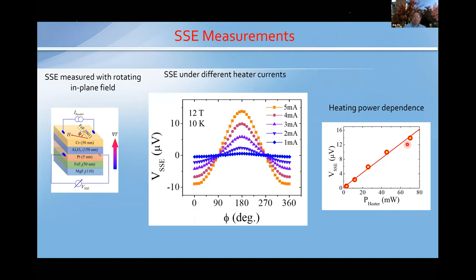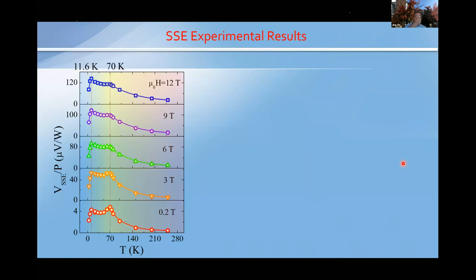Now let me present the data. I chose different applied magnetic fields along the easy axis, from 0.2 Tesla to 12 Tesla, which for iron fluoride is way below the spin flop transition field. This is as a function of temperature for different fields. At the lowest field, we have two peaks. One peak is around 11.6 K, and the other peak is located at 70 K, the temperature at which we start to see the exchange bias develop.